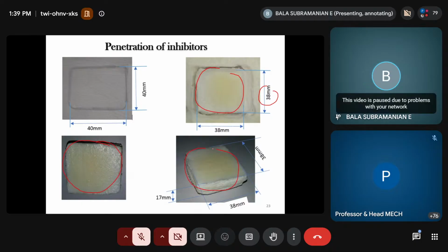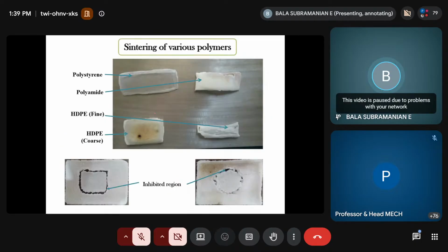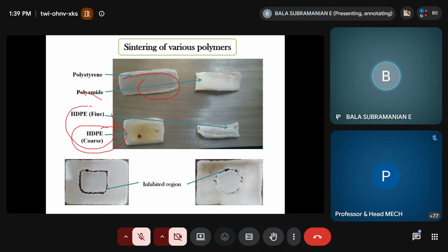Then we did the sintering phenomena with various heat sources and various polymer powders. HDPE coarse particles provided a good sintering. Still it is burning, but still we can control this. But other powder particles are not proper, and they are not able to do justice in the open atmosphere. So this is controlled in the open atmosphere.